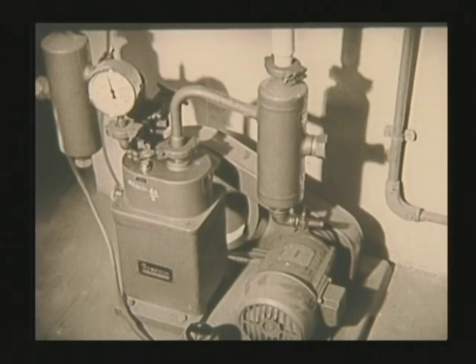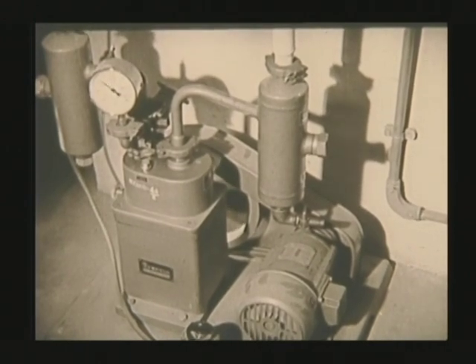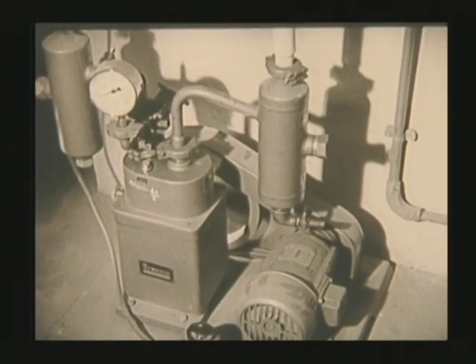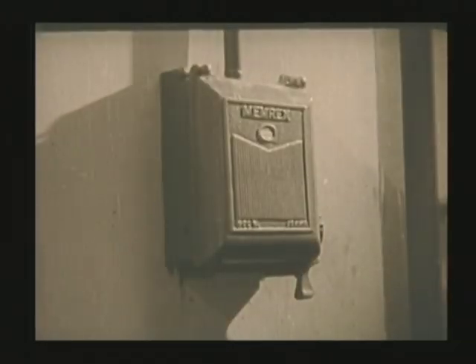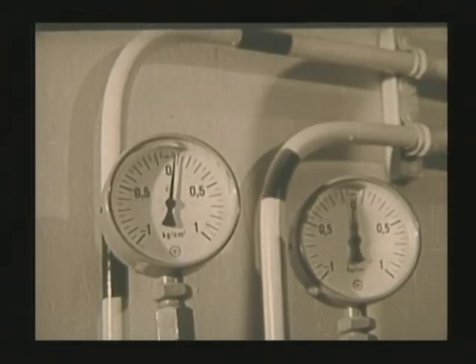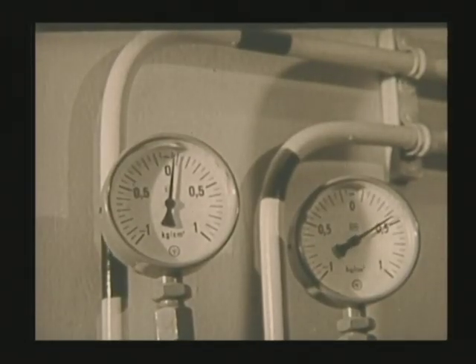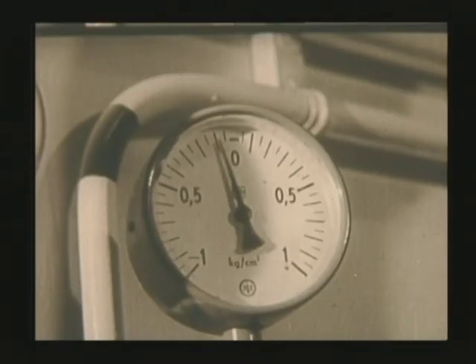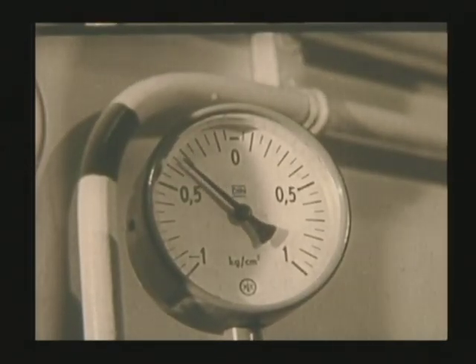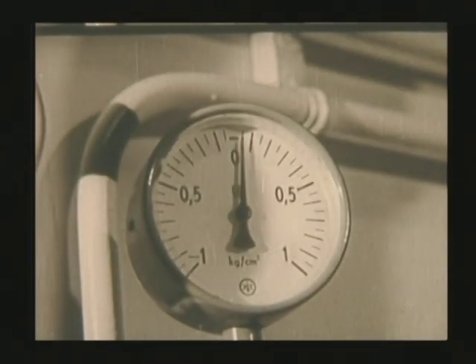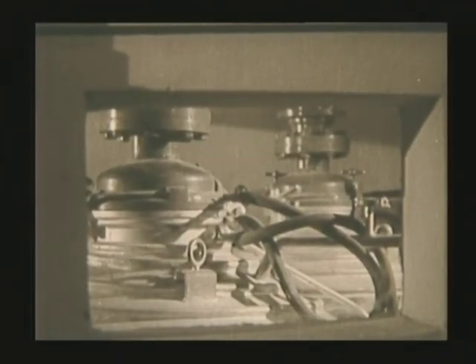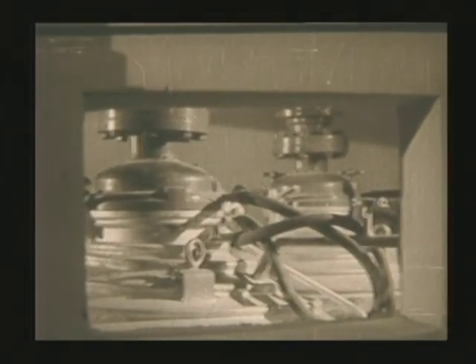The vessel is first evacuated by a vacuum pump and then filled with argon gas. A remote switch is then used to ignite the magnesium ribbon, which in turn initiates the reaction between uranium tetrafluoride and calcium. The reaction is instantaneous and violent. The vessel is cooled for 24 hours before the metal is finally obtained in the form of an ingot.